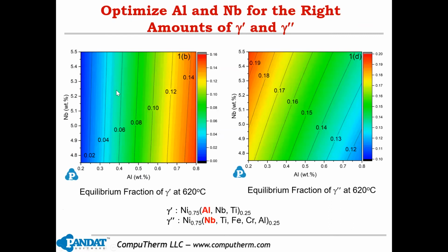The left figure is a fraction of gamma prime phase as a function of niobium composition and aluminum composition. As you can see, aluminum varies from 0.2 to 0.8%. The volume fraction of gamma prime can vary from 2% all the way to 14%.